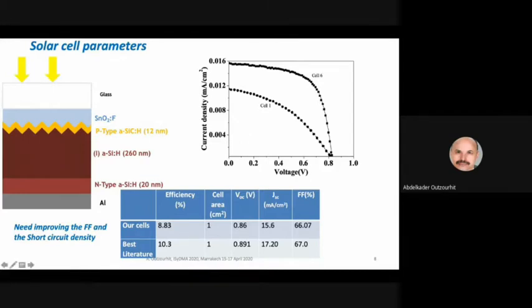The lower value of the short circuit current can be attributed to the fact that we used thinner films than what is usually used in the literature. So this can be increased by increasing the thickness of the absorbing layer. However, the small value of the fill factor is probably due to the resistive losses in our cells, as we can see in the following slide.